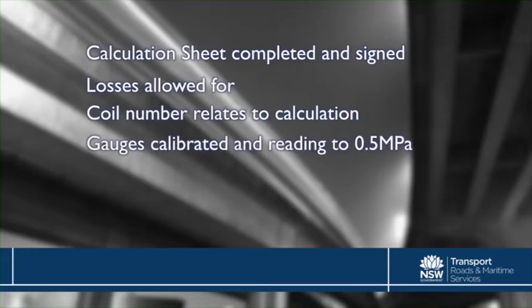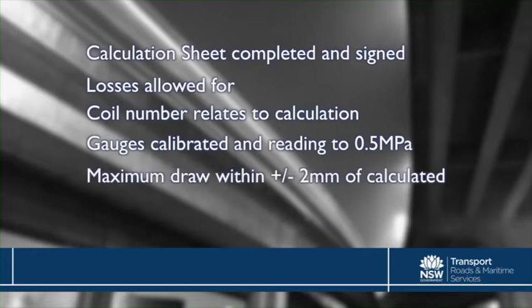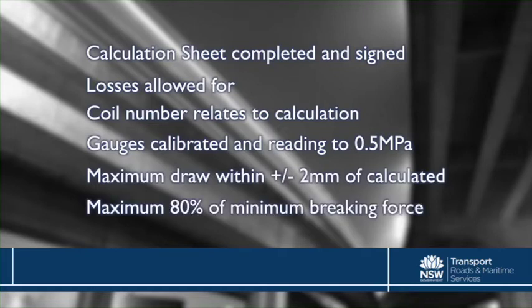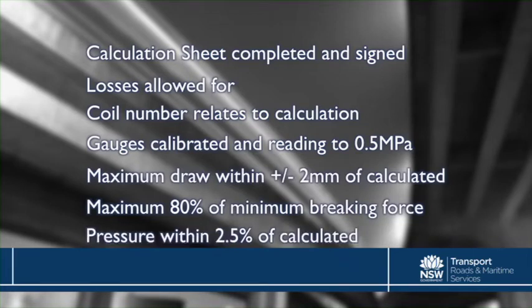The gauges need to be calibrated within the last 6 months, a minimum of 150 millimetres diameter and read to 0.5 MPa. The maximum drawing must be within plus or minus 2 millimetres of the calculated drawing, and the force on the strand must never exceed 80% of the minimum breaking force of the strand. And lastly, the pressure needs to be within 2.5% of the calculated pressure.